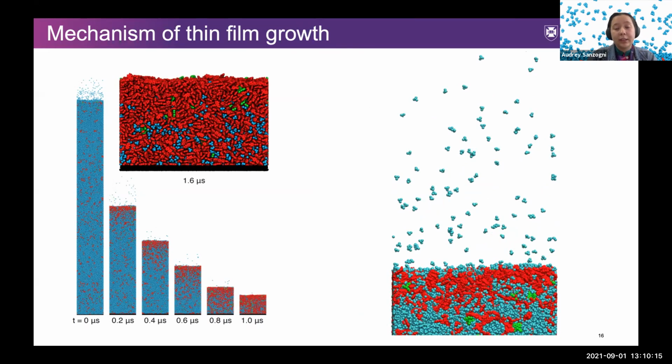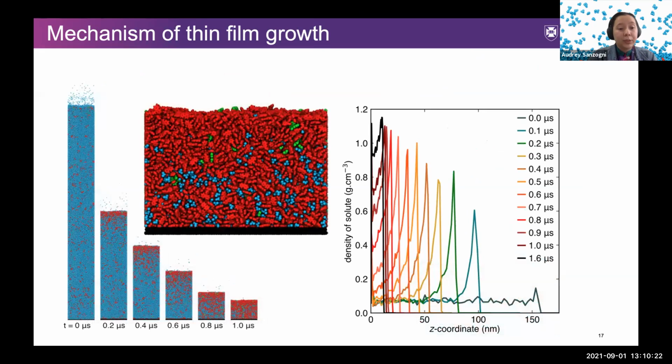We wanted to model this as accurately as possible because I wanted to see how the thin film formed over time, because there were proposals that the rate of chloroform removal would be such that the concentration of the solute would increase uniformly over the entirety of the system and eventually lead to a phase separation akin to spinodal decomposition.